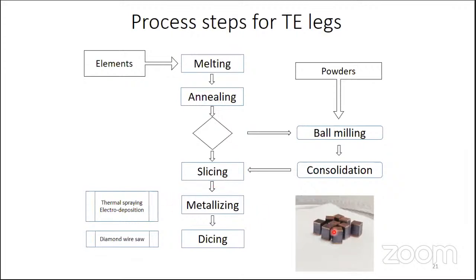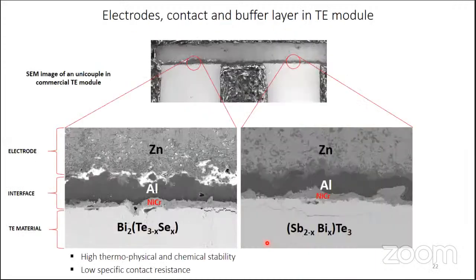But these legs as they are, you cannot bond with an electrode, so they have to be metallized by using some thermal spraying or electro-deposition. You have to metallize the semiconductor surface. And then the dicing you can do by using the same photovoltaic silicon wafer dicing techniques. You can use diamond wires or some other technique. You can slice it into whatever shape you want.